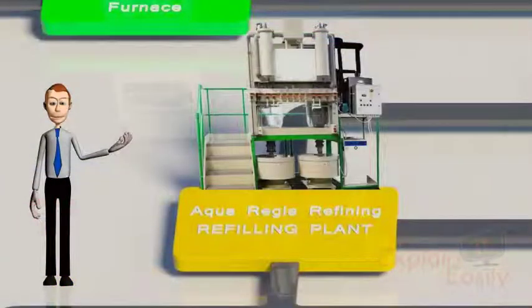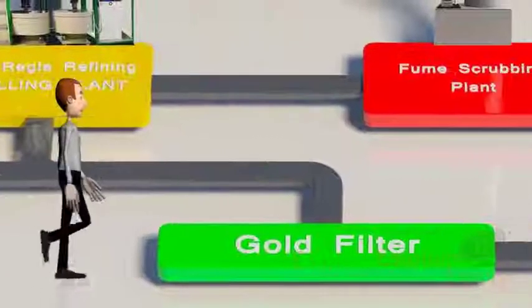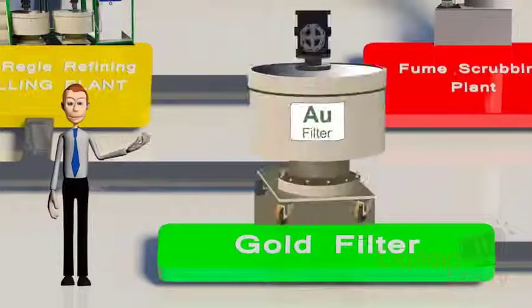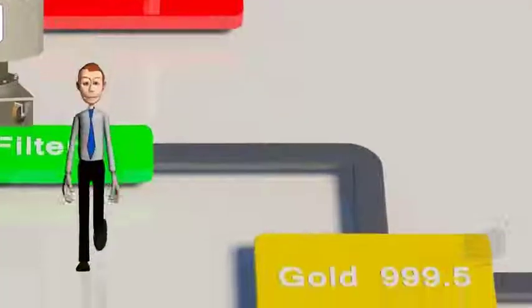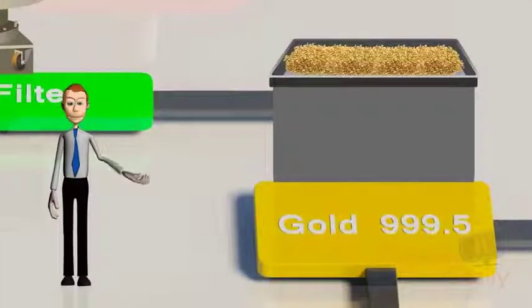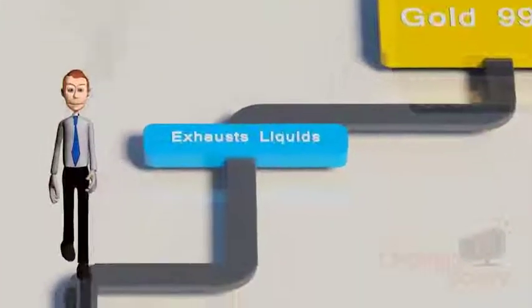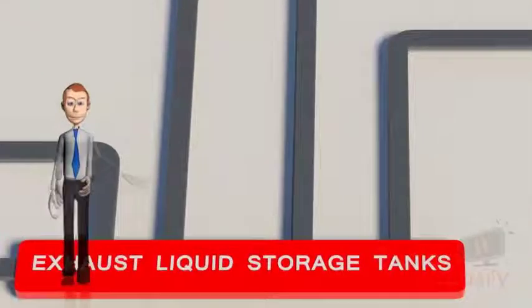Clear gold chloride solution is transferred to another reactor, where sodium metabisulfite is charged in as a reducing agent. This will then precipitate gold from the solution. This is monitored by good pH control and viewing glass reactor for the right change in color. The cemented gold is then filtered in the gold filter until it is ensured that entire gold is collected. This wet gold is 999.5 quality, and the liquids left out are transferred to exhaust liquid storage tanks.